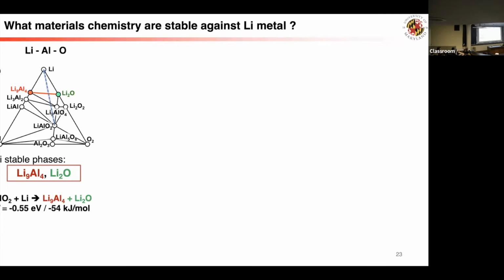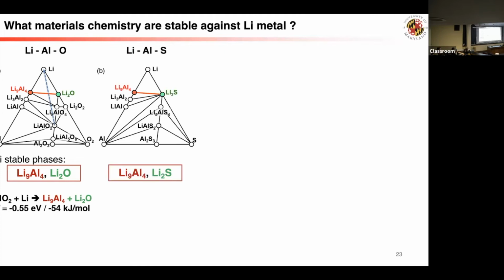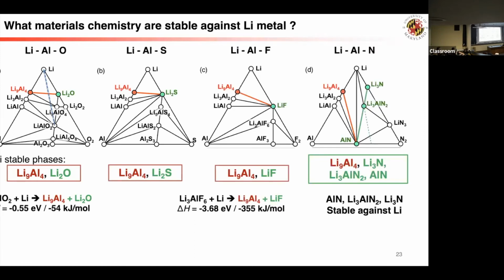And we can also evaluate what the reaction energy would be, right? So that's giving the driving force. Okay, so then with this, because you basically have everything in the database, you can just look through different materials. Let's say here we just change the ions, for the sulfide, fluoride, and nitride. For the sulfide, you still see these two guys. Fluoride also these two guys.